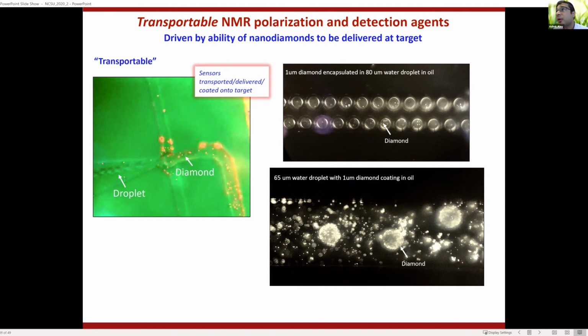There's a lot of interest now in reactions that have been shown to be accelerated, and there's a lot of hypothesis about these reaction accelerations originating from electric fields on the surface of these droplets, and we want to use the particles as electric field sensors so that you can measure the electric field on the surface of these droplets. But generally, what this illustrates is that because you can exploit through light the excellent spin properties of these materials, and these are materials in the solid state, these materials can be physically transported, and you can actually put them into things. And this is a very simple example of that.